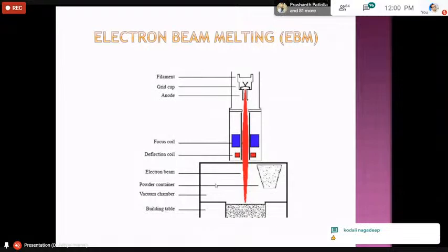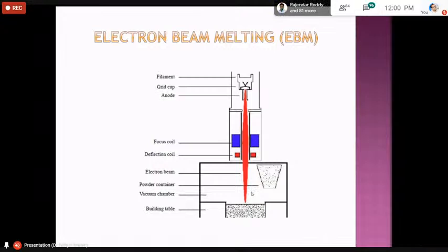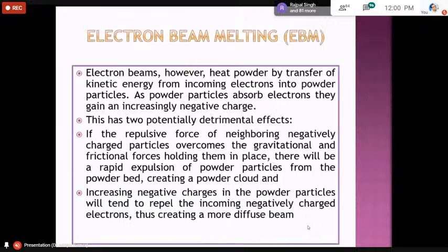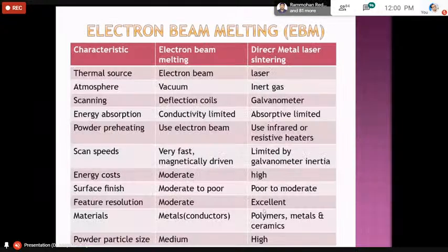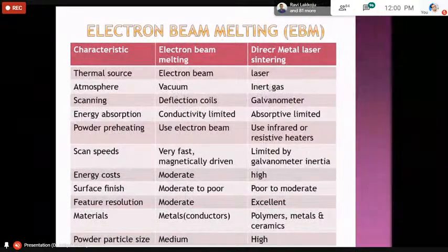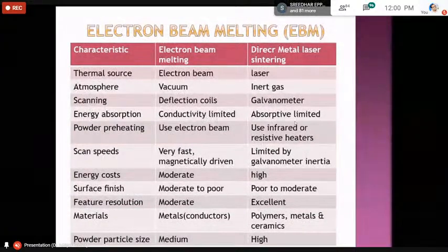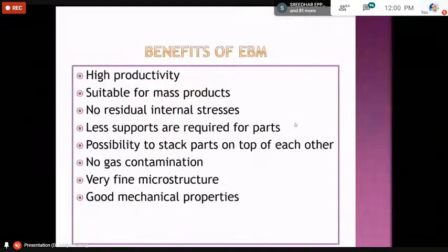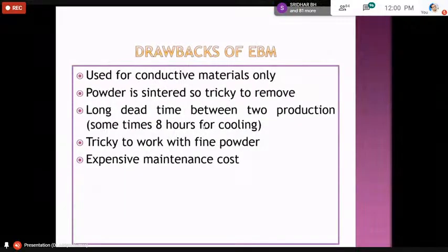But due to the creation of the vacuum, the cost of the process is very high compared to laser as a power source, and the size is also very limited. So the difference between electron beam and laser beam: the electron beam is performed under vacuum, whereas laser can be performed in inert gas, and mostly with conductive, highly absorptive materials. What are the benefits? Productivity is increasing, no residual internal stresses. Drawbacks: conductive materials only.